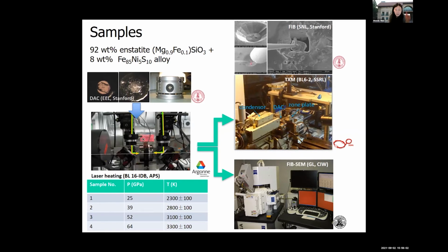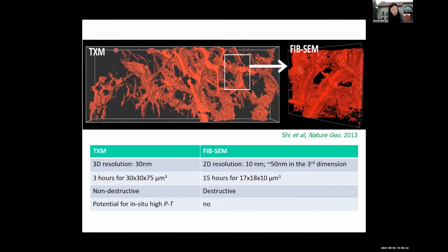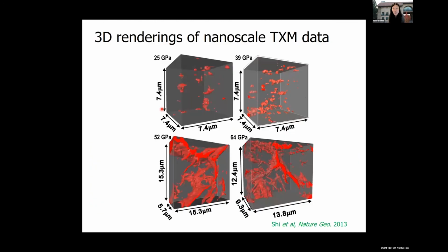We then recovered the sample back to ambient conditions and cut out a region of interest using FIB. Then we imaged the section using the nano-TXM. As a further benchmark, we also took a portion of the FIB sample, and Faye and his group at Carnegie helped us with serial sectioning via FIB-SEM. Okay, so here are the results for the 3D distribution of iron alloy melt